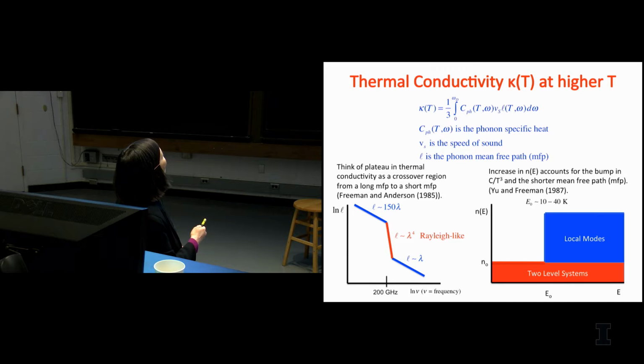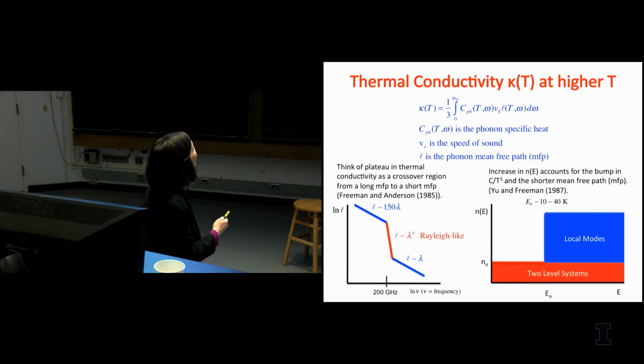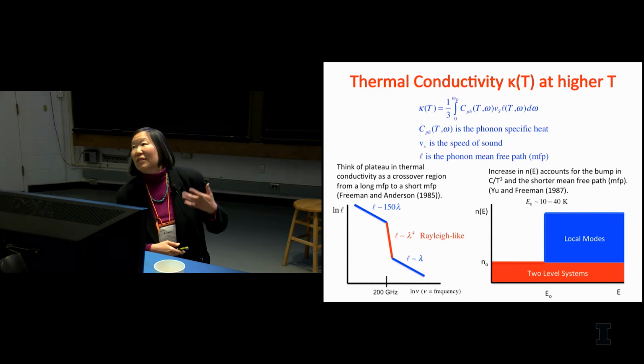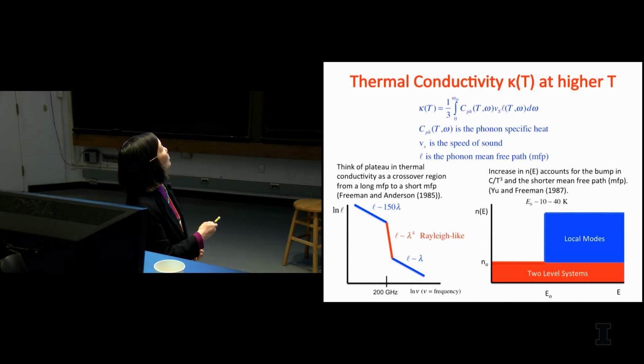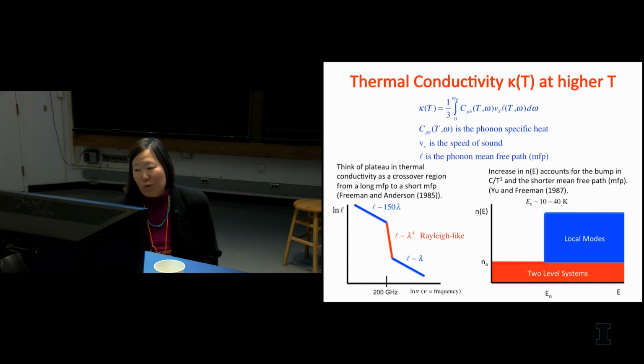Then you see this very rapid fall off. L goes as lambda to the fourth, as in Rayleigh-like scattering, and then a very short mean free path, where L is of order lambda. One way to describe this phenomenologically would be to say we have a density of states that are scattering the phonons. At low energies, you have these two-level systems. And then you have a rise in the density of states, some local modes. This rise would then account for more stuff to scatter off of, and a shorter mean free path. And the rise occurs around, say, 10 to 40 Kelvin.